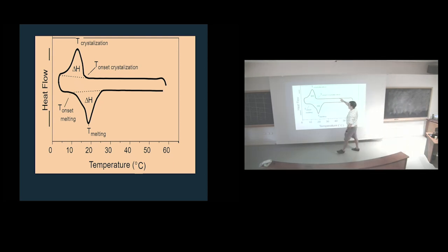So here we go from hot to cold, and we get an enthalpy of crystallization, which is the area under the curve. The temperature of crystallization here is shown as the peak, but most self-respecting chemists maybe talk about the onset. I put both and let everybody scream at each other. I'm too busy. And then here's the melting part. And then you can get the enthalpy of melting and the temperature of melting, the two parameters that we needed in order to calculate the chemical potential. So at least conceptually, you've addressed one aspect of the crystallization process.